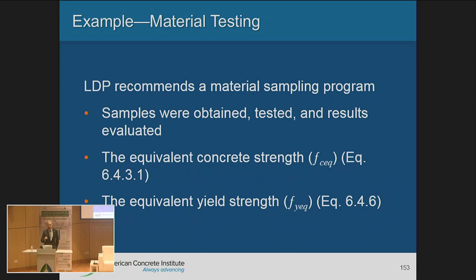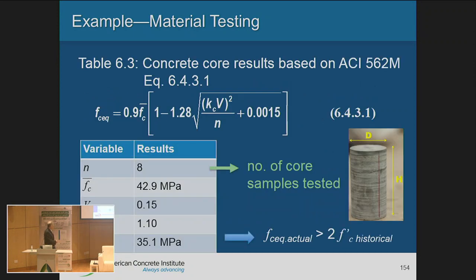So rather than going in and strengthening the structure, the engineer said, let me do some testing. Let me go through a testing protocol. So they did, he took 8 samples, and they found out that the average is 42.9. By using those values, the equivalent concrete's compressive strength was 35. And if you look at it, it's more than twice the historical data. So you can see with the testing, you get a little bit of advantage.